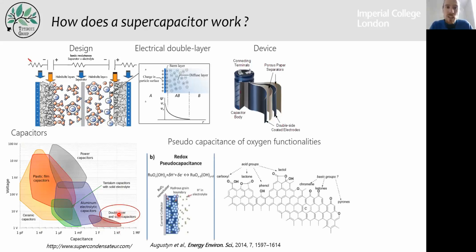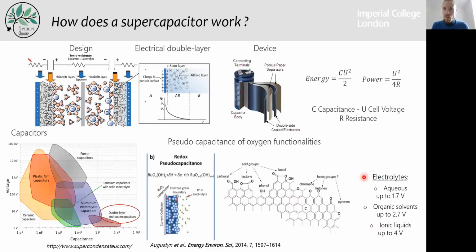So what I'm going to talk about in this talk is more about porous carbons. So we will have the electrical double layer effect, but we will also encounter some pseudocapacitance that corresponds to the redox pseudocapacitance that we saw in the previous slide, and that is due to the oxygen functionalities on the surface of the carbons. And just to give you an idea of how we relate this to the energy and the power density, the energy is proportional to the capacitance times the cell voltage squared. And if you want to have high power, you need to have very small resistance of your device.